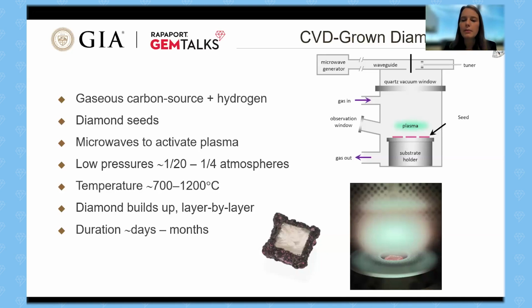And you can see here on the bottom right, you have a CVD diamond in growth. In fact, this was taken at the GIA labs, the CVD growth lab. So you have your CVD diamond, and above that, you have that plasma of the gaseous species. And again, depending on the quality, the color, the quantity of samples you're going to be growing, it can range from days to months.